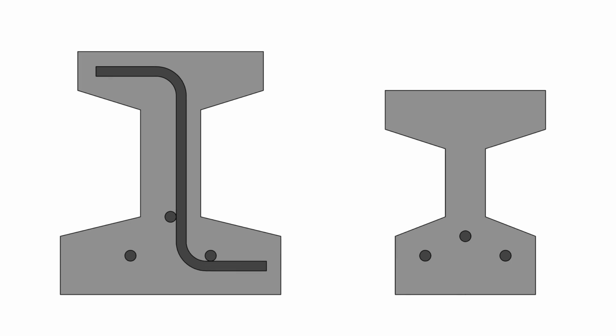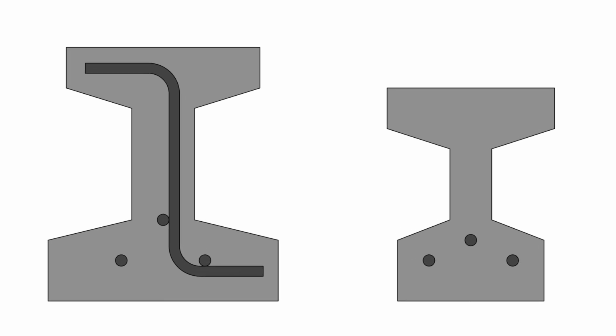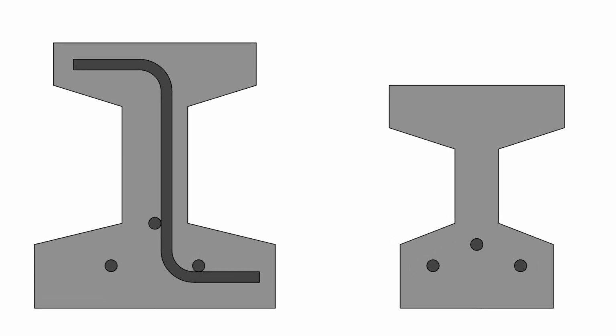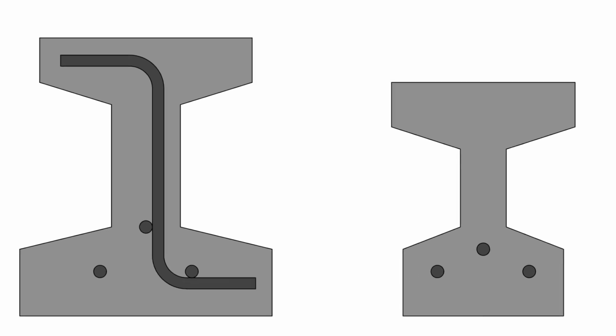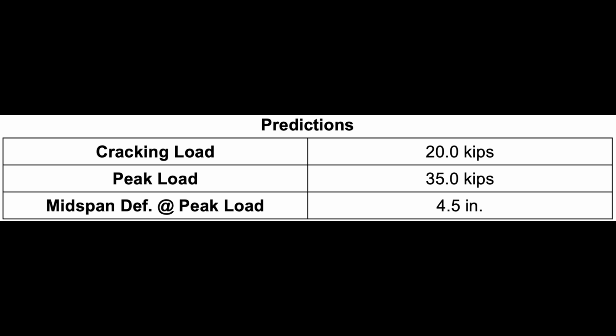It also means the geometry of our beam isn't driven by the stirrup dimensions like in a traditional concrete beam, which means our stem can be thinner and our flanges can be narrower. Our predictions for this design are shown here on the screen, where we predicted a cracking load of 20 kips, a failure of 35 kips, and a peak deflection of 4.5 inches.